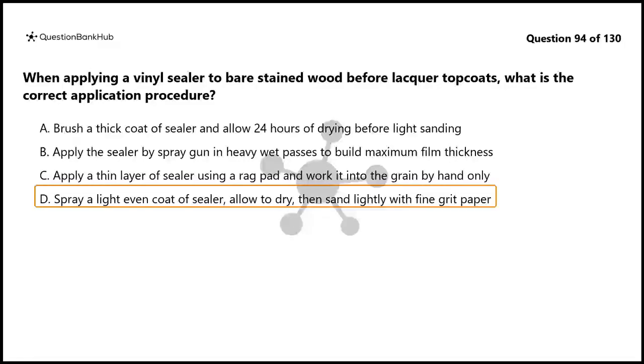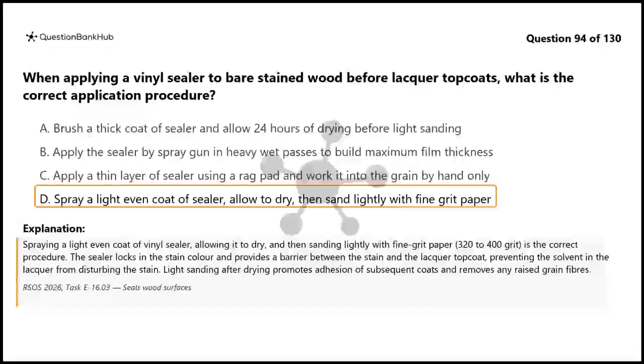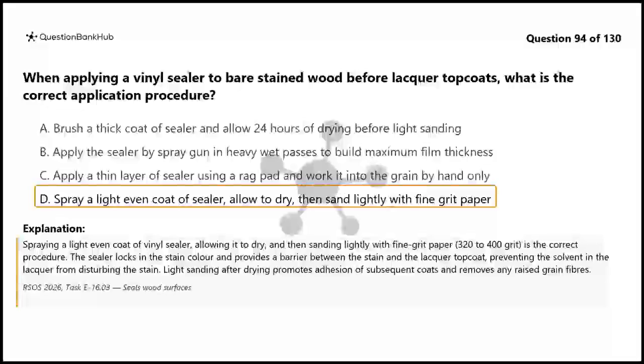The correct answer is D. Spraying a light even coat of vinyl sealer, allowing it to dry, and then sanding lightly with fine grit paper, 320 to 400 grit, is the correct procedure. The sealer locks in the stain color and provides a barrier between the stain and the lacquer topcoat, preventing the solvent in the lacquer from disturbing the stain. Light sanding after drying promotes adhesion of subsequent coats and removes any raised grain fibers.